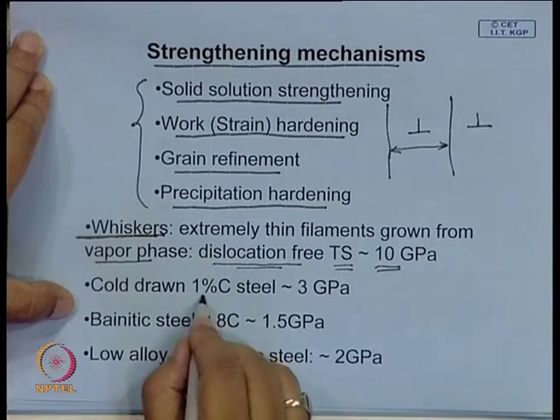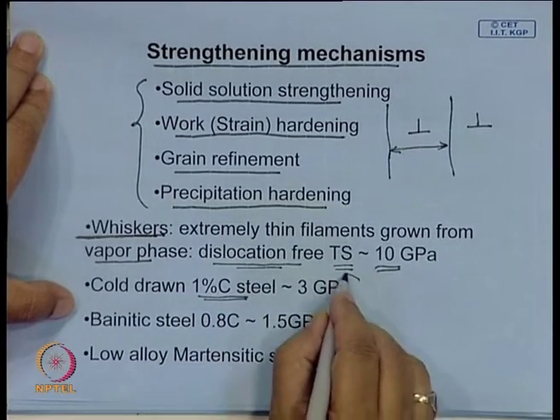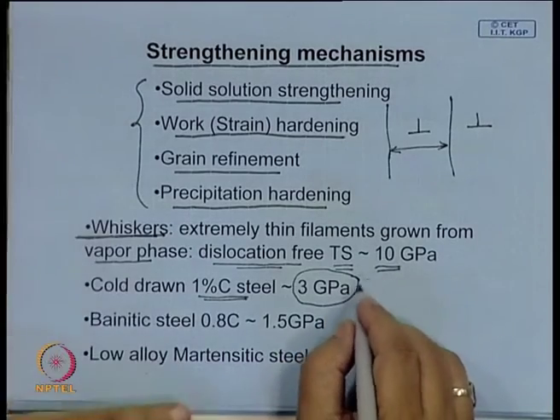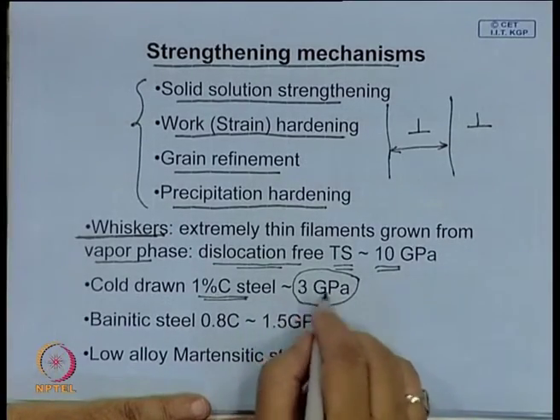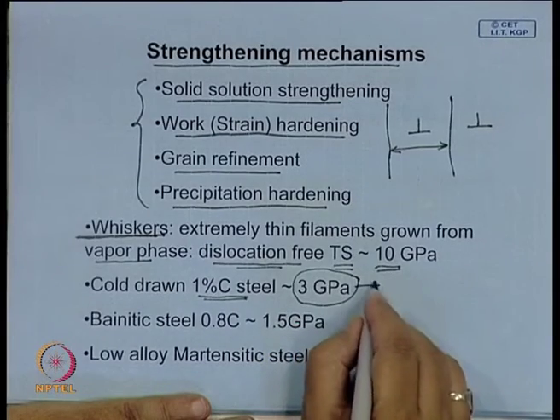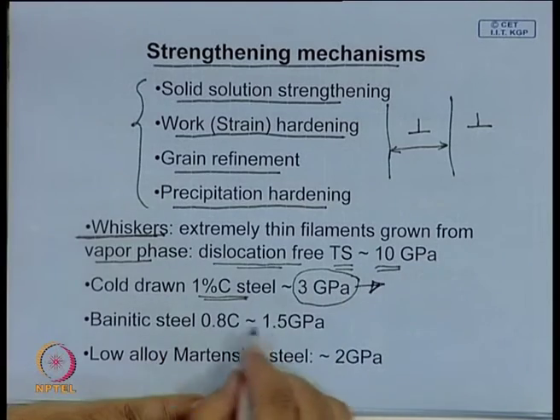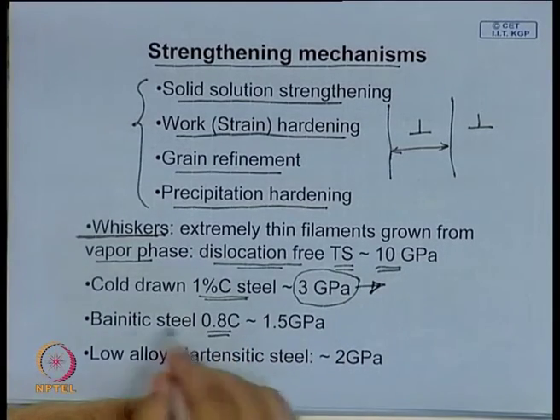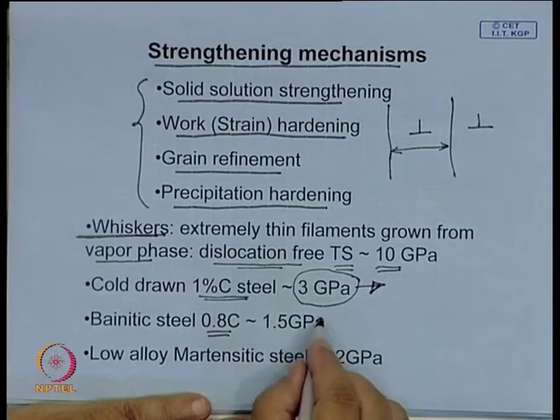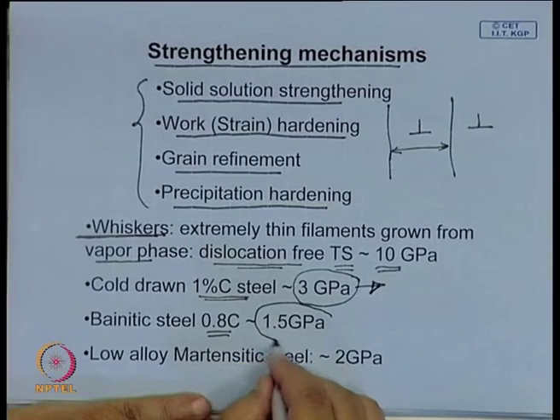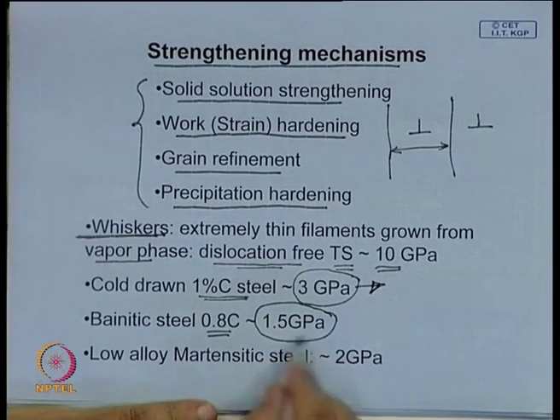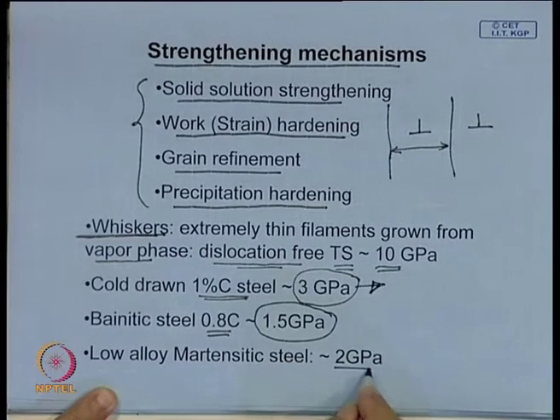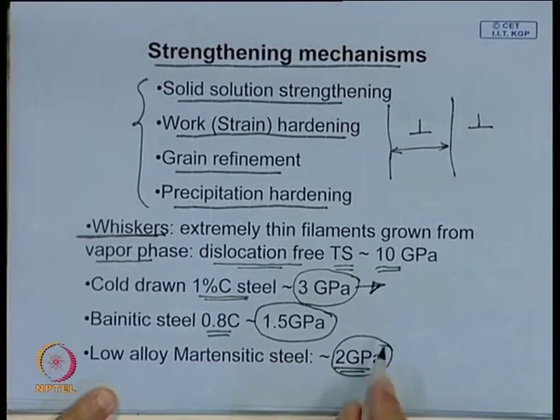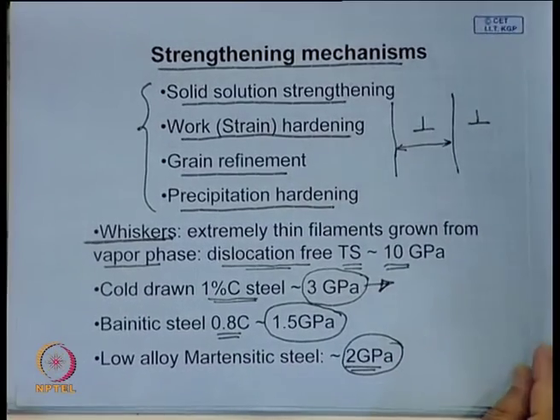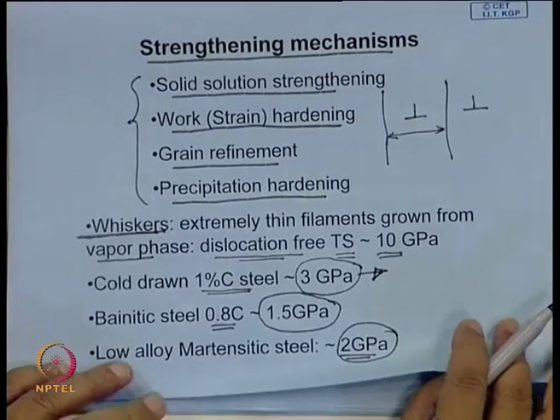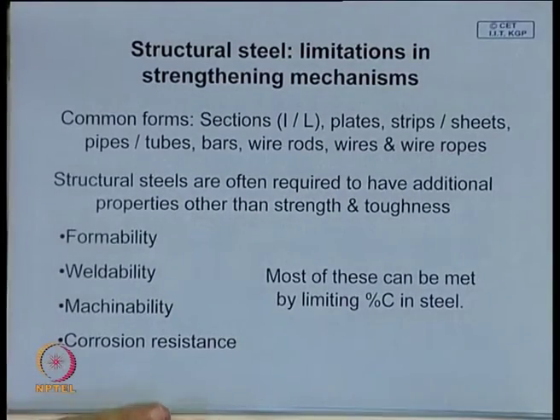By cold drawing 1% carbon steel, we will see how it undergoes a very special deformation process, by which you can achieve this in actual practice. Bainitic steel, the strength will obviously depend on the amount of carbon that is there. If it is 0.8, you can get this level of strength, whereas with low alloy martensitic steel, you can get strength of this order. But very often the structural steel that we use is not martensitic, and let us see how we can strengthen them.